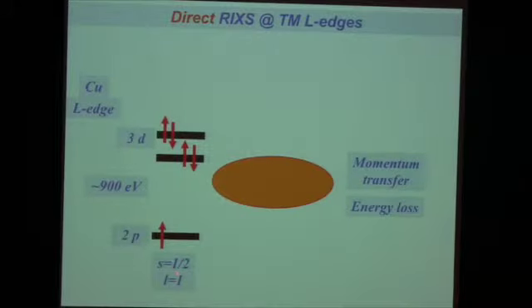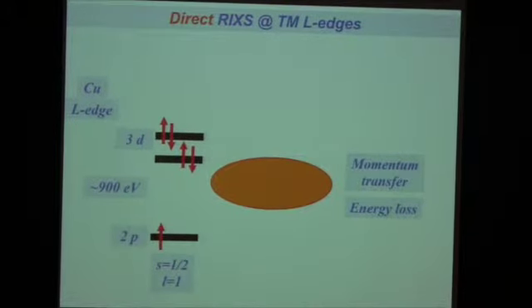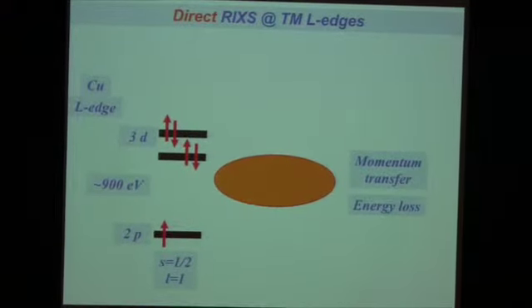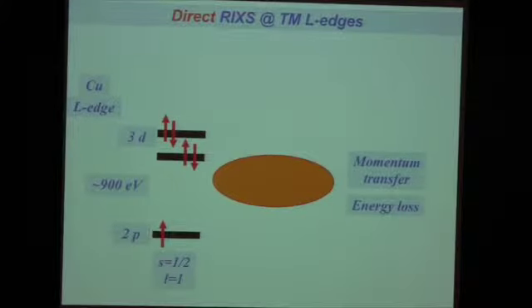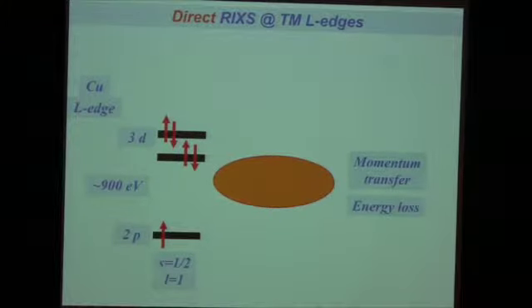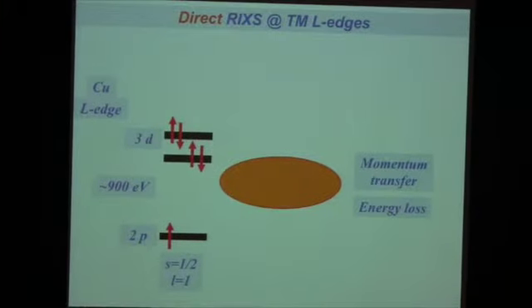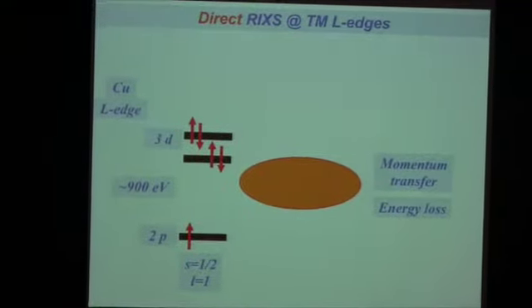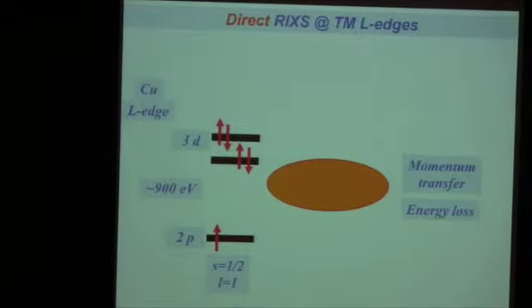And now let's look at this intermediate state for a bit. Actually, I have a spin 1/2 in a 2p state, which is an angular momentum L equal 1. So I have a spin and I have an orbital momentum, and I have spin-orbit coupling in the core. Actually, spin-orbit coupling in the core of, in this case, a copper ion is huge. It's about 20 electron volts. It's not a small perturbation.